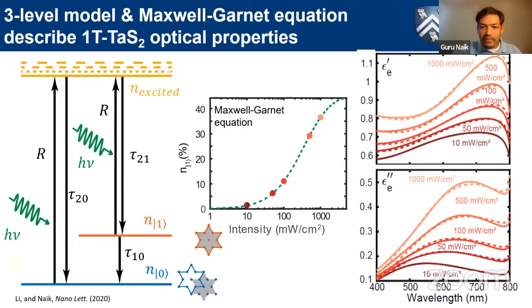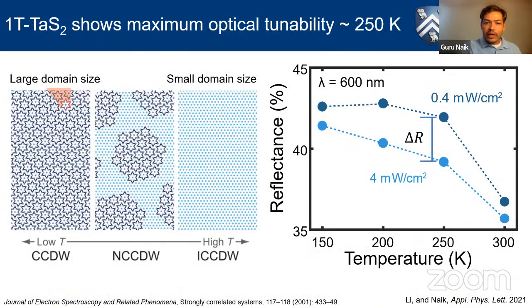And about the same time, there were also a few other papers that came up which did TEM studies and X-ray diffraction studies to show that light indeed changes the stacking of CDW domains. So that was quite interesting, to say that there is some intensity-dependent or nonlinear optical response simply coming from how these CDW domains reorganize or stack on top of each other. Now if this was the case, then there must be some dependence on temperature, because temperature changes the domain size. So what if we reduce temperature? What do we see in terms of this tunability or nonlinear optical properties?